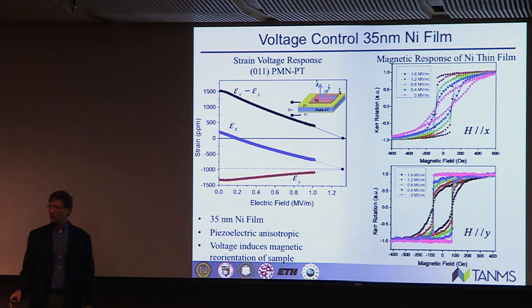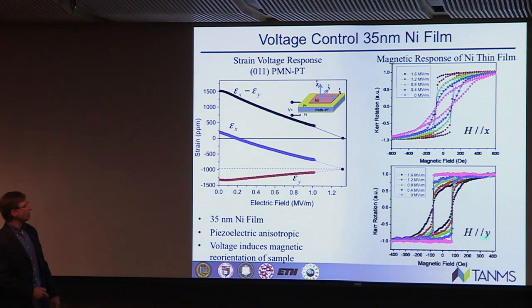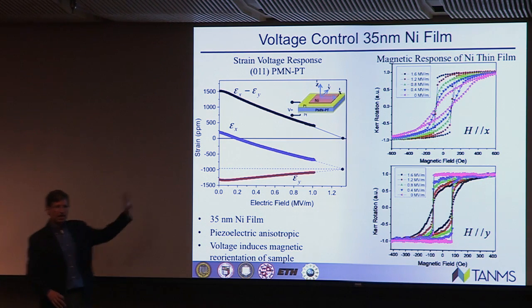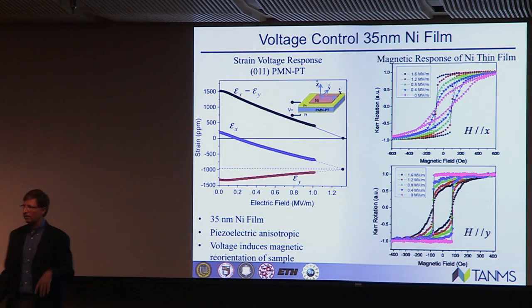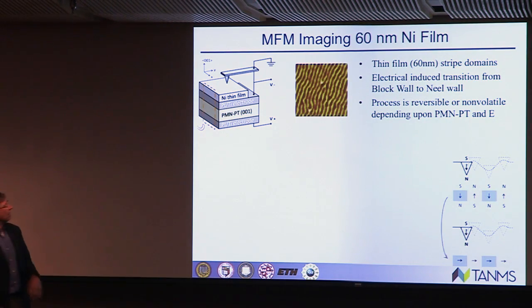Now we've actually reoriented the easy axis from the y direction to the x direction. So we've rotated it by 90 degrees, and these are through Kerr measurements. Okay, so now you've bought that, hopefully, on 35 nanometer thick film. Now let's go to something slightly thicker, 60 nanometers.